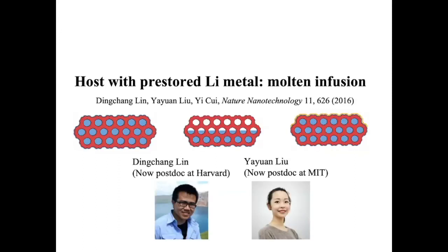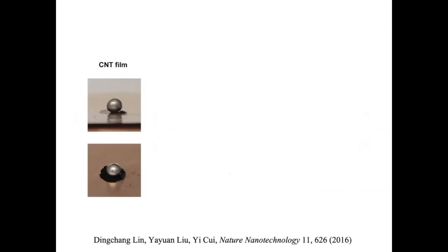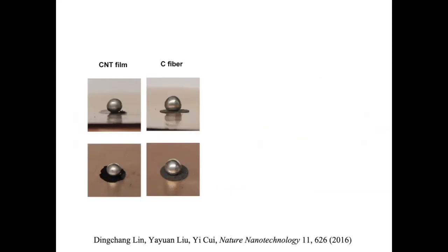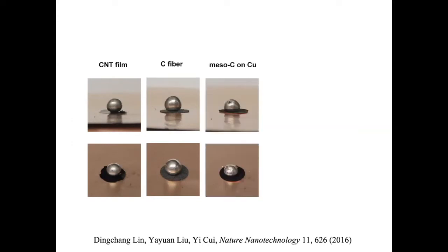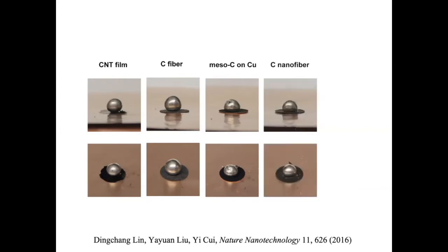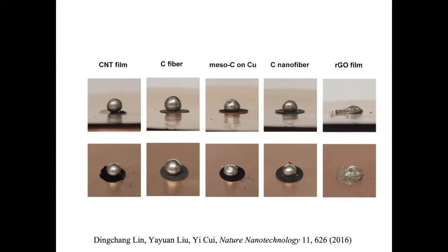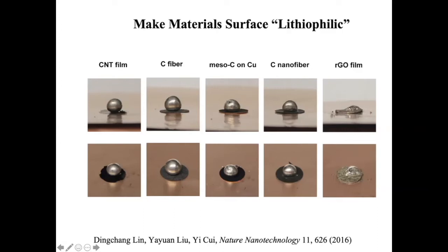So Ding Chang and Yao Yuan really pioneered this area in my group, and I have shown this before. If you melt lithium, we want to develop a molten lithium process, onto different materials. Lithium metal does not really like to wet on many materials, until one day Ding Chang and Yao Yuan tried reduced graphene oxide. It melts, it goes in. We discovered lithium has this wetting property, similar to water hydrophobic, hydrophilic. Now we call it lithiophilic or lithiophobic.